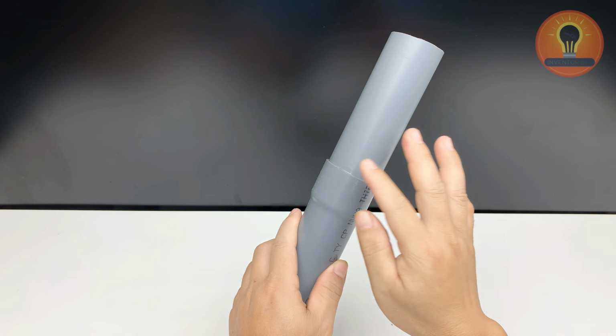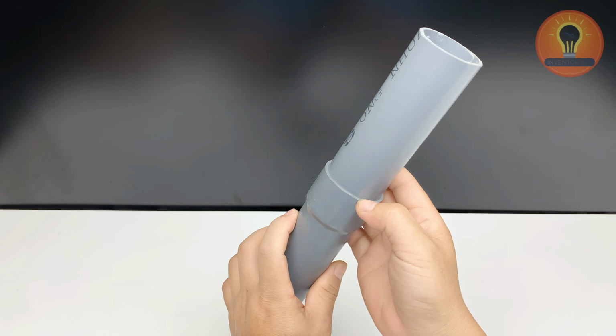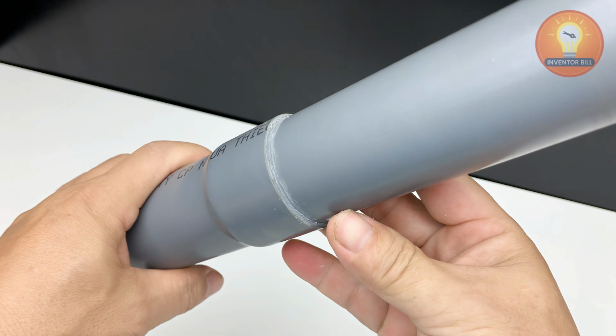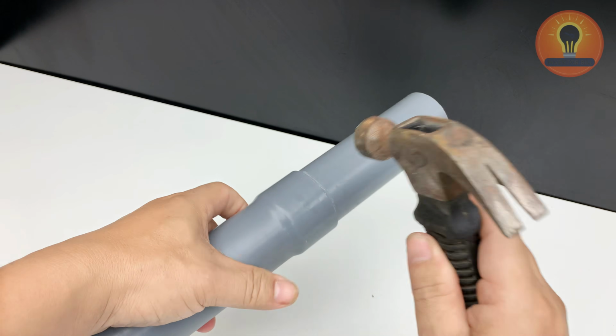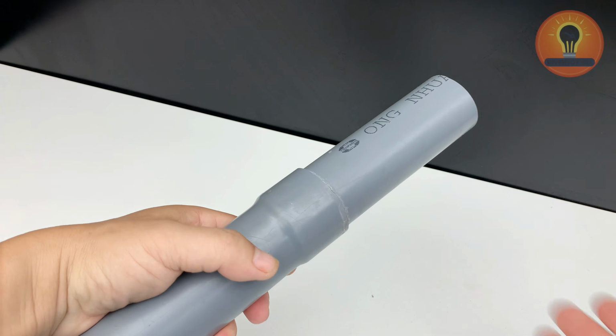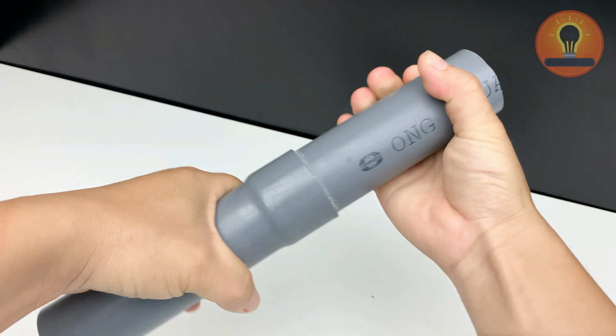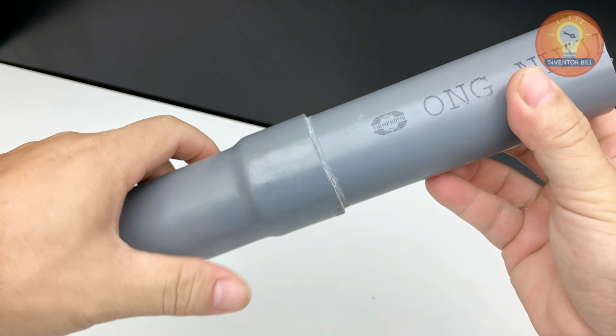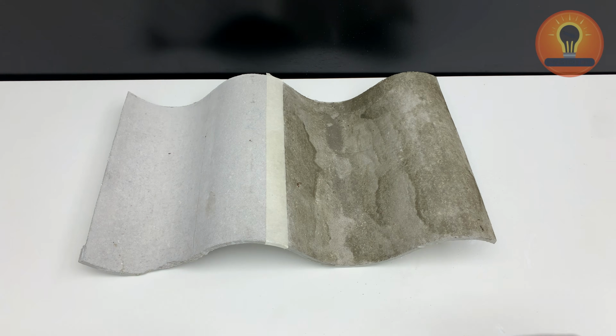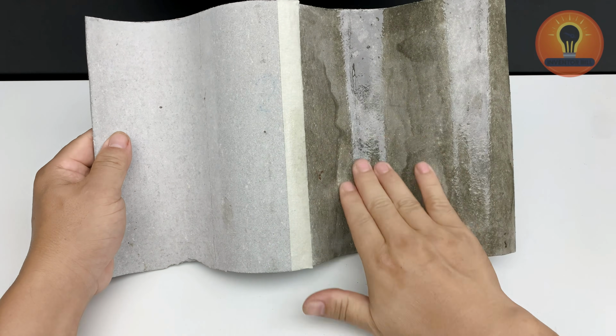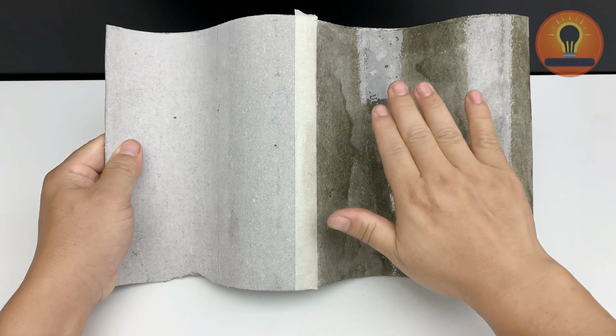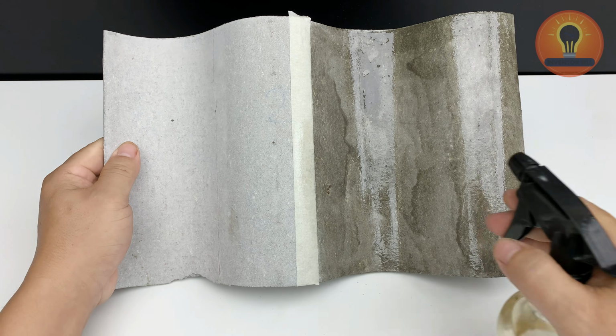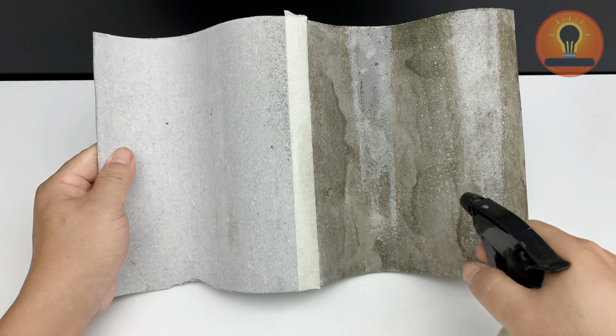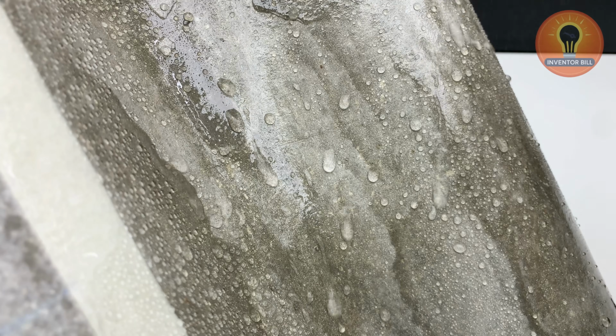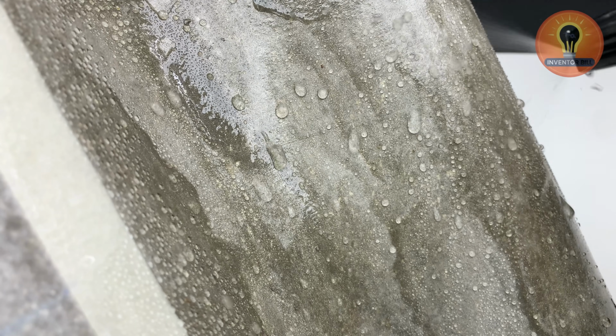Next, check the PVC pipes. Try pulling them apart. They stay firmly connected, even when applying strong force by hand. They don't come loose. Tap them lightly and the bond still holds. Now move to the fiber cement board. Spray water onto both sections. The untreated side absorbs water, while the coated side repels it. The difference is clear, though.